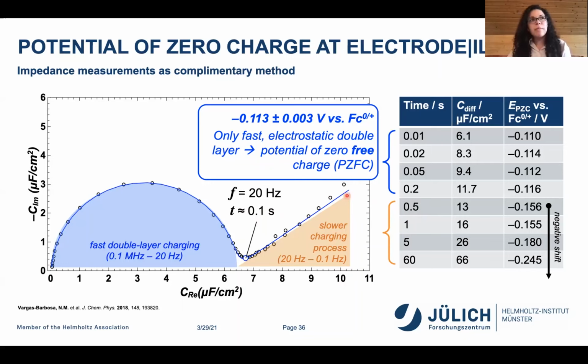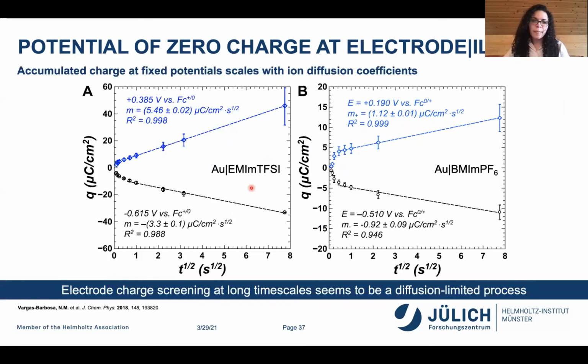0.5 is pretty much a Warburg element. So diffusion. So we said, okay, diffusion, that slower, okay, is this consistent with our charge traces? So we look at that a little bit more carefully. We have here now the charge of these immersion measurements that we did, plotted as a function of the square root of time for 2 different ionic liquids. And we observe actually relatively good correlations.